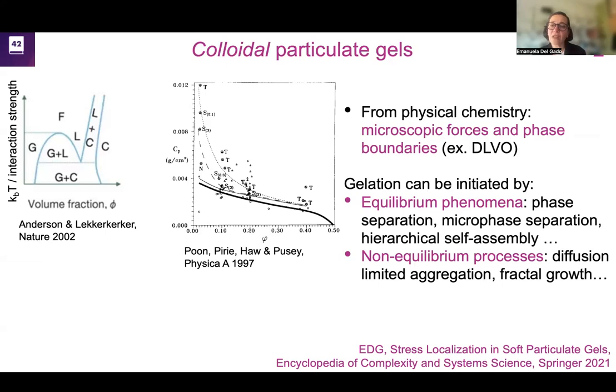If I have a suspension of particles and I know the physical chemistry of the suspension, so the particles, the surfaces, the solvent, then I have some tools to predict when the particles will aggregate, when they will tend to form, for example, crystalline solids, when they will tend to form glasses, and so on. These are examples of phase diagrams that people have drawn or measured from experiments to make sense of where these types of gels are more likely to form, because in order to get a gel, I need a strong interaction. So they will tend to be along, for example, this phase boundary between phases of clusters or really dense liquids of particles that nearly phase separate from the solvent.